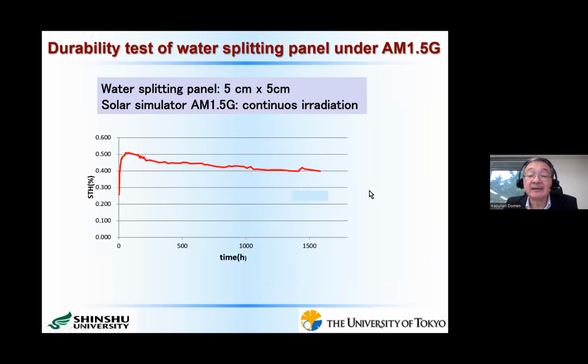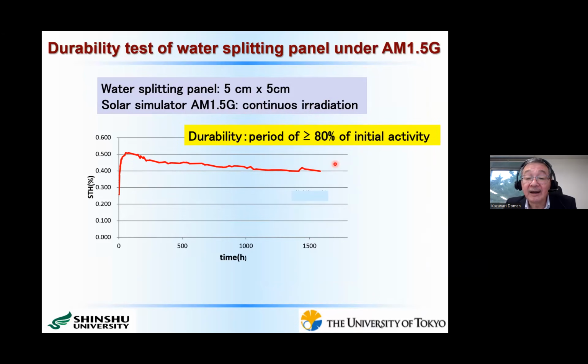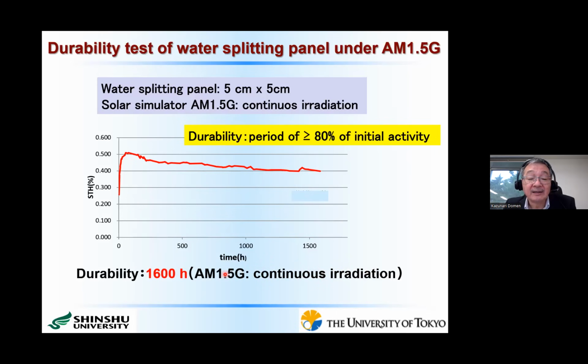In addition, we also examined the durability under continuous irradiation of sunlight. Our definition of durability is the period that maintains more than 80% of initial activity. Here I show one of the typical experiments using this kind of water splitting panel, and this is 1,500 hours. From this experiment, we evaluated that under continuous irradiation, I mean irradiation day and night, the durability was about 1,600 hours. Then we consider that under field test conditions, I mean there is day and night, and also clear days, rainy days and cloudy days, and considering the Japanese weather conditions, we evaluated that the durability will be about 1 year. So we decided to construct such field test systems.